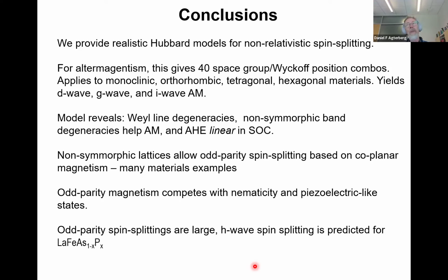Yeah. So when we did the general Ginzburg-Landau analysis, we found 3 different ground states. And those ground states did break up into ferroelectric-like, nematic-like, and also this S1 cross S2, or this odd parity magnet. Now, I meant in that sense, they're different, but you're absolutely right. In the odd parity case, the odd parity magnet, we also can have nematic order, like you have already pointed out in your work.